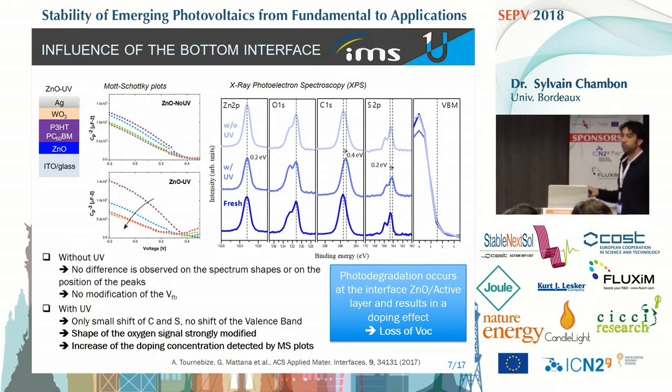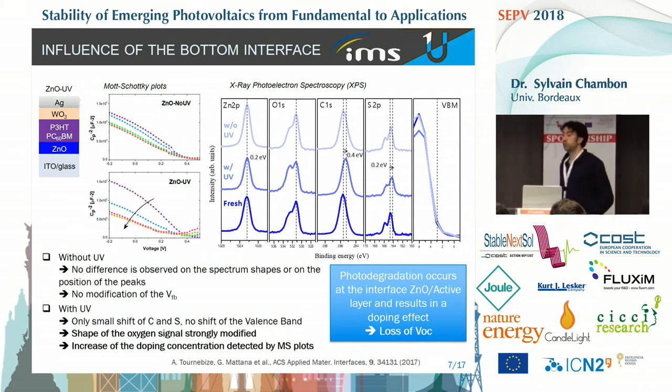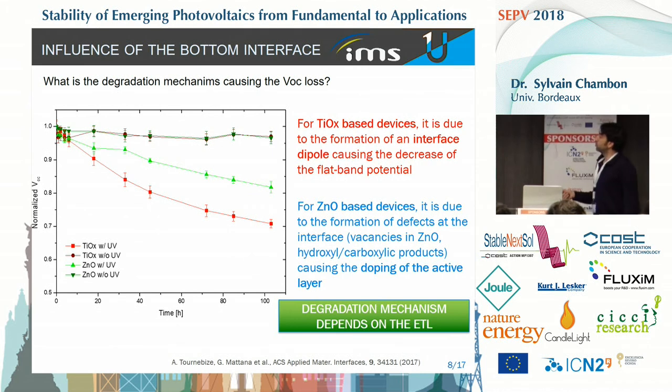And the combination of the two analyses led us to the conclusion that there had been some photodegradation at the interface between zinc oxide and the active layer, and this degradation has also led to the loss of VOC. So the conclusion of our study was that in both cases, titanium or zinc oxide-based devices, we observed a drop of the VOC. But the origin was different. In one case, we attributed it to the formation of a dipole, and in the other case, we attributed it to the formation of some defects at the interface.